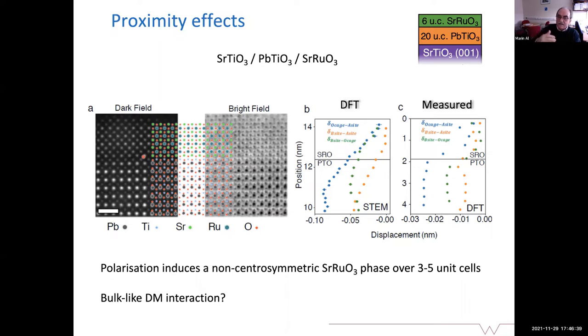It's more than a couple of nanometers. So it's about 3 to 4, even more unit cells. So you see here, in terms of nanometers, it may go a couple of nanometers down as a DFT calculation. This is the distance between the oxygen and the A site, and then the B site and the A site, and so on and so forth. And that goes with the symmetry breaking. And then you see here the real measurement, by measuring the real position of the atoms